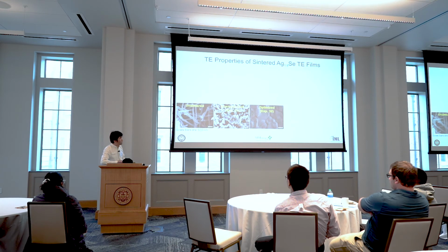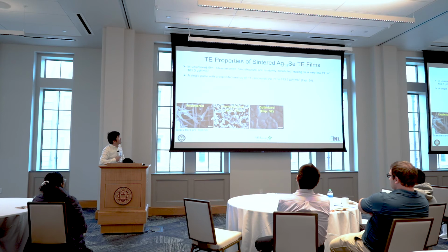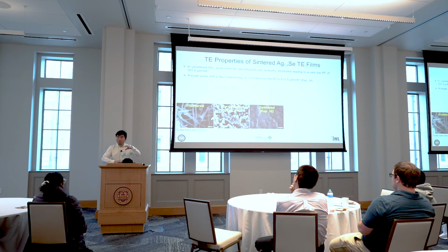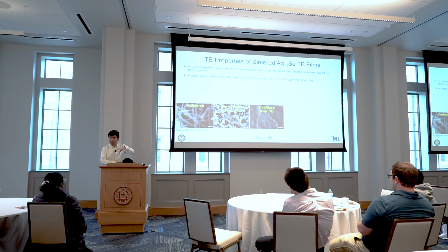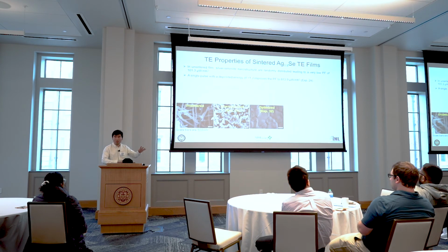Okay? Initially, say, these are unsintered. The unsintered film has a power factor of 100-ish. And then if we put a single pulse, remember we're using this pulsed light for sintering, if we put one pulse, that power factor was able to improve to 800. But you can optimize a little bit, it wouldn't change that much.